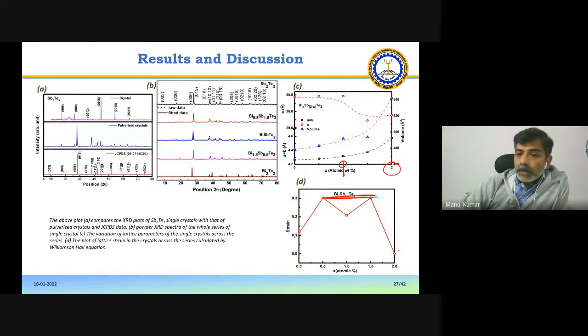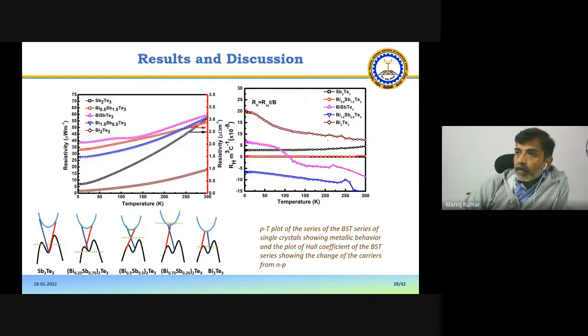So because of the strain present in the material, we see a different nature or positioning of the Fermi level. This is strain. So from Sb2Te3 to Bi2Te3, we can imagine this was p-type. And then when we increased the bismuth in place of antimony, here we had the Fermi level in the gap. For this composition, the resistivity was maximum. So we can say that here we have the Fermi level well within the gap.